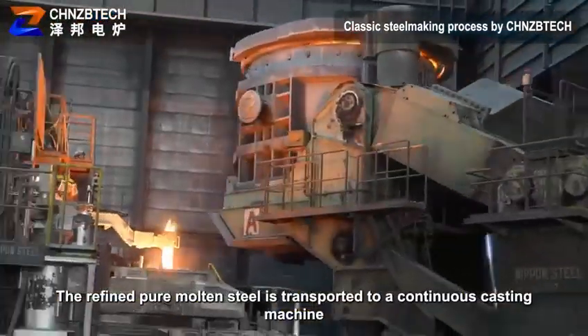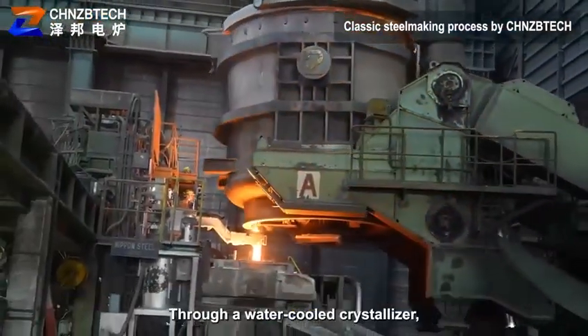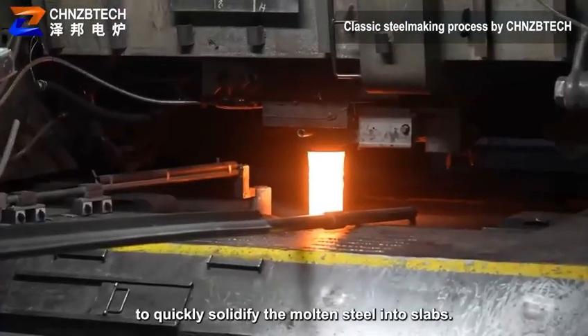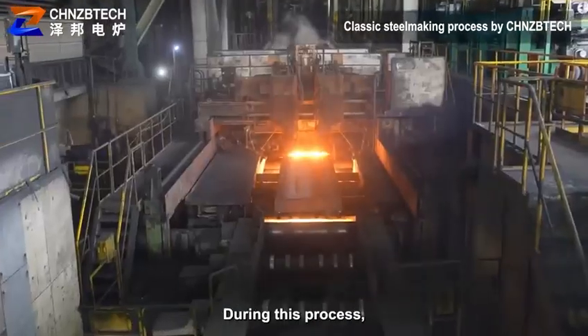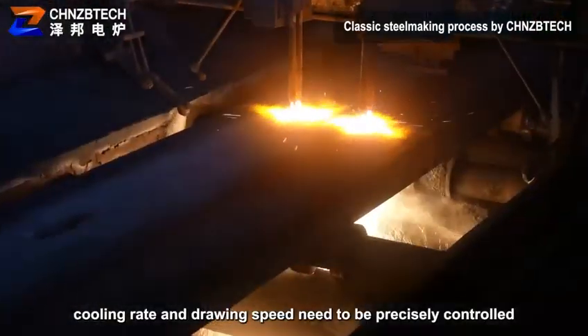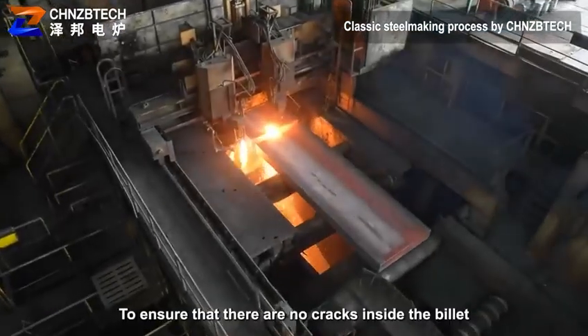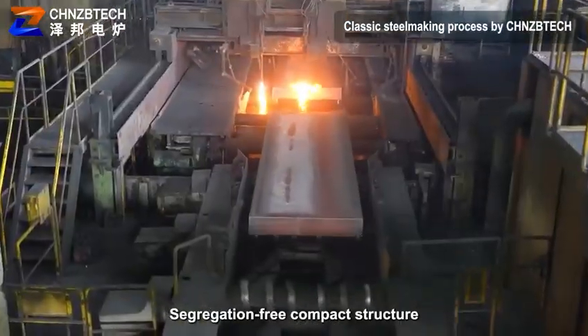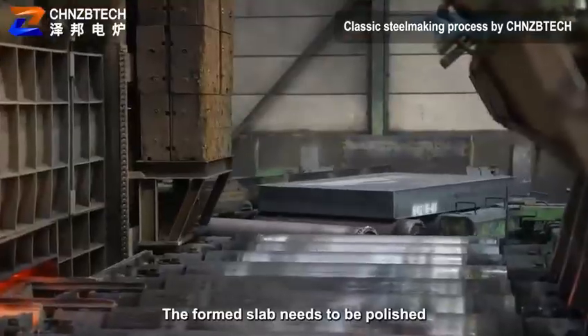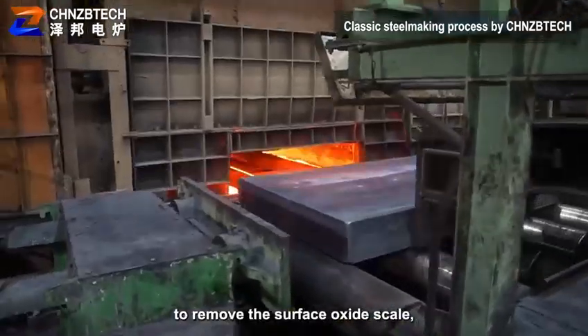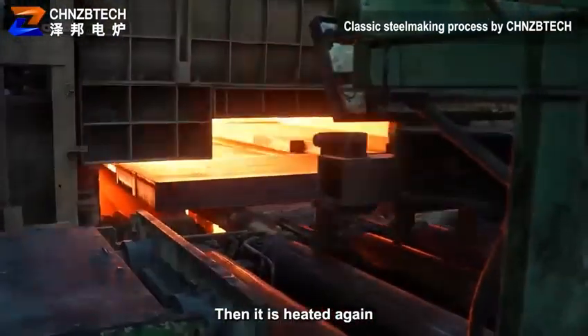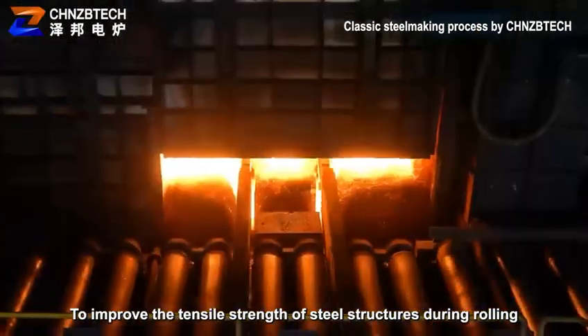The refined pure molten steel is transported to a continuous casting machine through a water-cooled crystallizer to quickly solidify the molten steel into slabs. During this process, cooling rate and drawing speed need to be precisely controlled to ensure that there are no cracks inside the billet, and a segregation-free compact structure. The formed slab needs to be polished to remove the surface oxide scale. Then it is heated again to improve the tensile strength of steel structures during rolling.